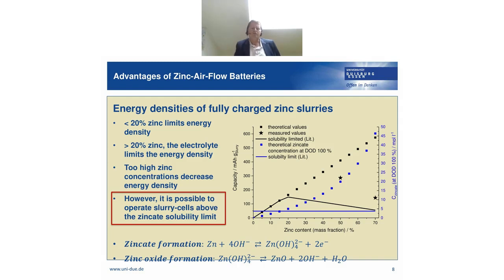So when we look first at the reaction equation, zinc is converted to zincate when we discharge the battery, and once the electrolyte cannot dissolve zincate anymore, zinc oxide precipitates. I don't want to go into all of the details in this graph, but interesting is the blue line, which goes horizontally at the bottom here, and this shows that only around 4.5 moles per liter of zincate can be dissolved, and even for this value you require some additives to stabilize the zincate in the solution.